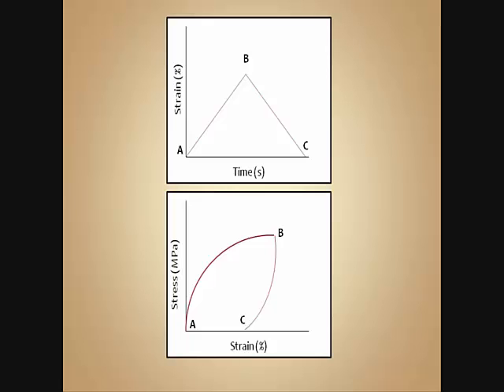The B value will be our final value of strain and is chosen as 4%. This is chosen based on material behavior and lies within a quasi-elastic region of our polymer sample. Quasi-elastic means that we get some elastic behavior, but at the end, some plastic deformation is experienced. The quasi-elastic region, though, does tell us that we should not experience fracture due to over-deformation of the sample.